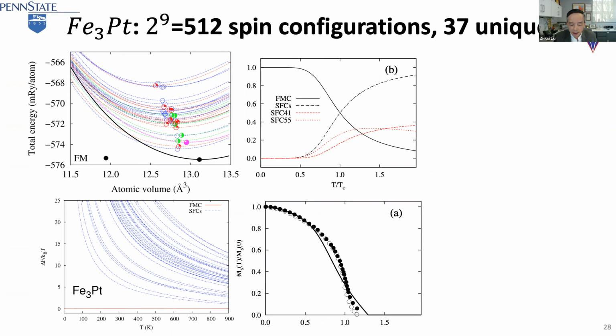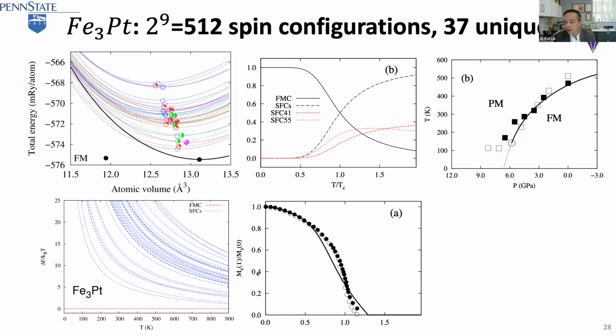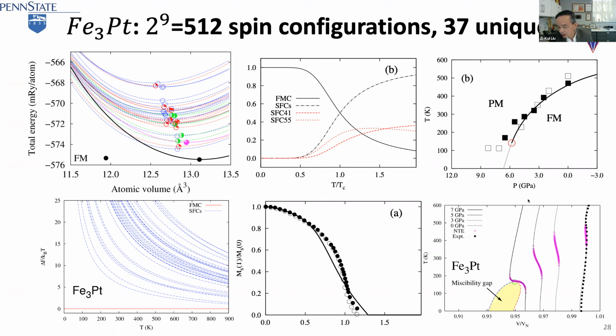But we can calculate the magnetization. We can calculate the phase diagram, the temperature-pressure phase diagram. Even more important, we can do the temperature-volume phase diagram. Each line here is a fixed pressure. This is the ambient pressure. The volume is going to increase first as temperature goes up, then start to decrease, then increase again. So in this purple area, you have a negative thermal expansion.